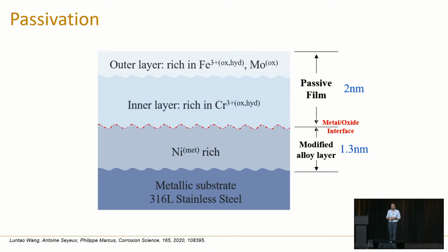But it really wasn't until maybe the last 2 decades that scientists or electrochemists started realizing that passive films are not these well-behaved blobs that obey these wonderful models like the Verwey model and so forth. They're actually usually multi-layered, where you've got a layer closer to the substrate, an outer layer and an inner layer perhaps, and you get different concentration gradients through these passive films, even though they're really thin.